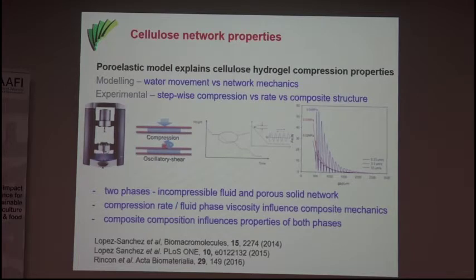So how did we measure that? Well, this is in Jason Stokes' lab, a very neat way of doing it. We just do sequential compression and then measure the strength. So we compress at different rates, stop, measure the strength, press again and stop and measure again. What is shown here is what happens when you do it at 3 different rates. So you get higher responses with the faster rates for this reason.